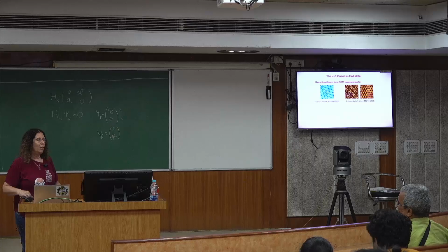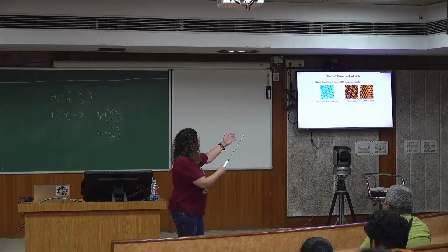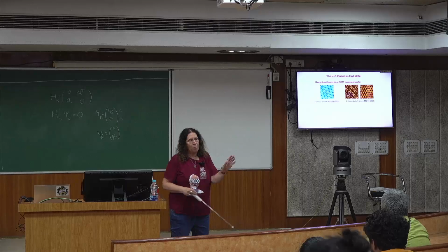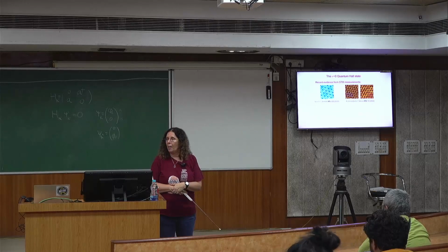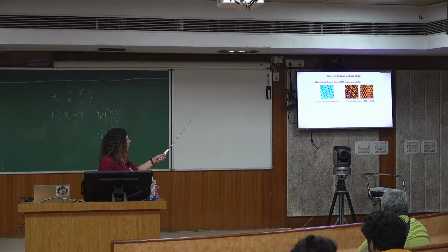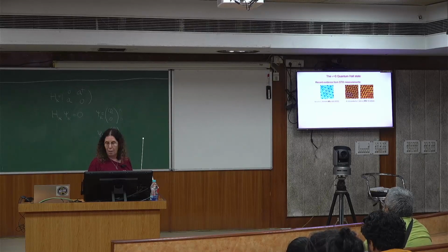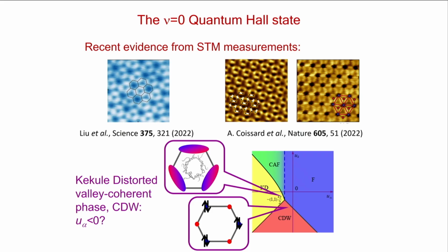It's a material with very high dielectric constant, and he can control the screening from very high to low screening, and by tuning it, it changes the image. In some regime he sees something that is probably not giving any charge density, but there is a regime of parameters where you see Kekule and you also see the charge density. So you clearly see charge ordered phases. And these are the two phases from the phase diagram.